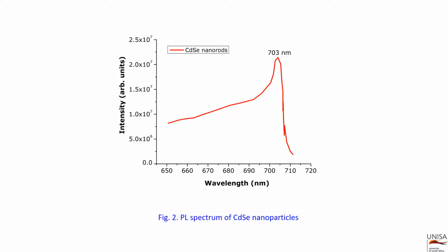This indicates a narrow size distribution of the cadmium selenide nanoparticles, possibly corresponding to the recombination of luminescence of shallow traps and surface defects, localized excitons, and intrinsic excitons. The large band at 703 nanometers can be attributed to the radiative recombination from deeper defects and impurity levels. Figure 2 displays the photoluminescence spectra of cadmium selenide nanoparticles, where a band usually attributed to impurity and vacancy complexes at 1.76 electron volts is observed, corresponding to the energy band gap of the cadmium selenide nanoparticles.